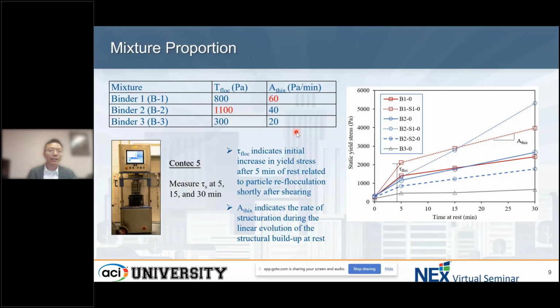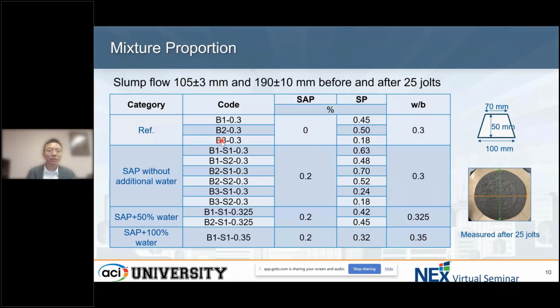Yeah, and then here shows the mixture proportions. We have done many mixtures. So the first category is reference, and the second category is a mixture made with SAP but without additional water. So we can see here the water binder ratio is 0.3. So in the label of the mixture, the label is 0.3, and the SAP with 50% water is 0.325 water binder ratio, and the SAP with 100% water is 0.35. We use the additional water only for